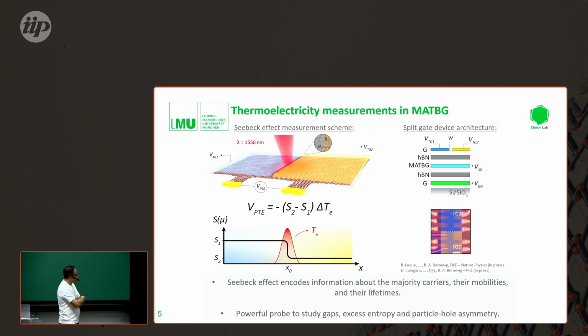And the second ingredient, of course, that we need here is some temperature gradient. The temperature gradient we achieve here with a laser beam that is very low power, but if you shine the laser beam directly at the junction, you create a temperature gradient, which you can roughly approximate to be linear around the junction. So if we treat the laser beam just as a heating source that induces the temperature gradient, we can measure the photovoltage across the device and extract the Seebeck coefficient from the system.